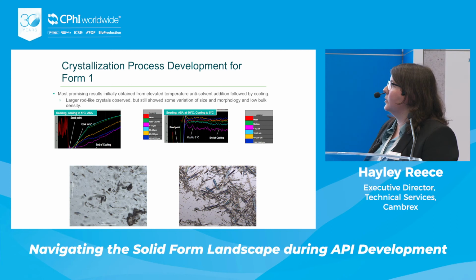And what we see there is that the particles for that one are pretty poor. We're seeing some agglomeration, we're seeing breakage of particles, very, very small particles as well. Definitely not an ideal process. The Blaze Metrics data again shows us the trends with regard to the number of particles for each particle size level, so anything below 10 microns or between 10 and 40 microns, all the way up to 150 to 1,000 microns.